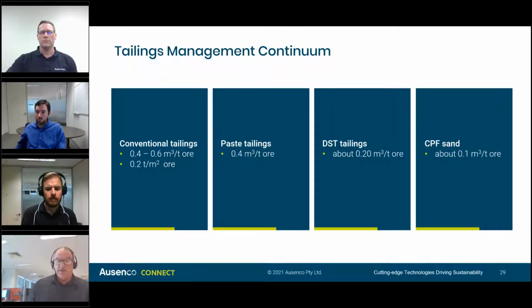So the high cost of implementing and operating can make a technology appear unfeasible. However, not only economic issues must be considered. Aspects focused on the environmental impact of construction and operation, and potential risk to community and environment, may make alternatives like dry stacking feasible compared to hydraulic pumping to tailings dams. So over the years, we have witnessed a progressive improvement in technologies as we move to dry disposal. This particular picture indicates how we have less water reporting to our dams, from the conventional side of 0.4 to 0.6 right down to 0.1. So there's been a good move towards removing the amount of water that has gone out to tailings.